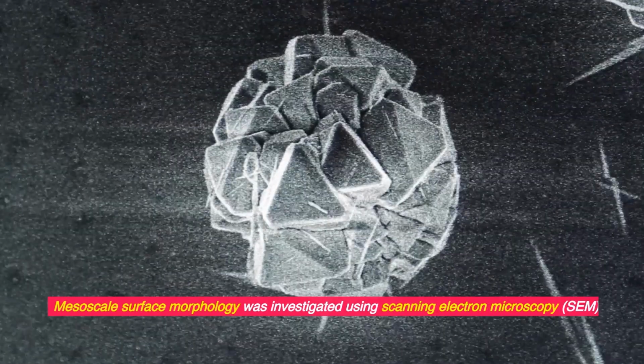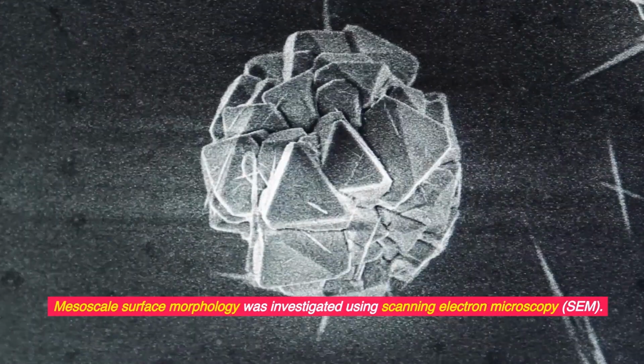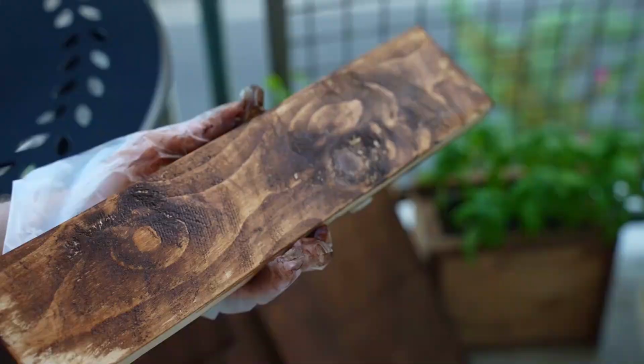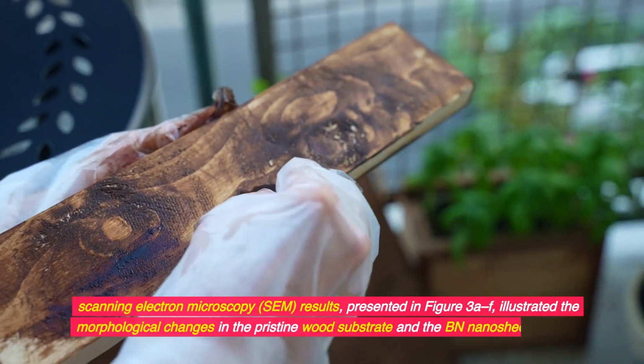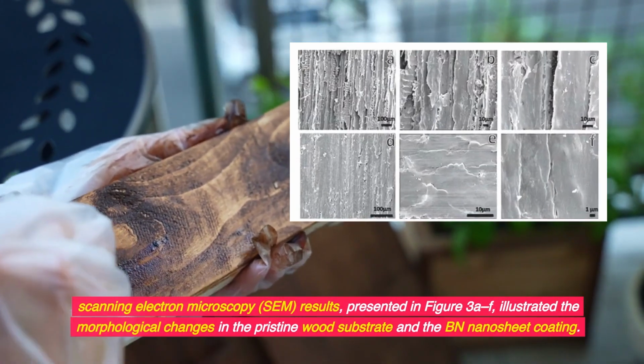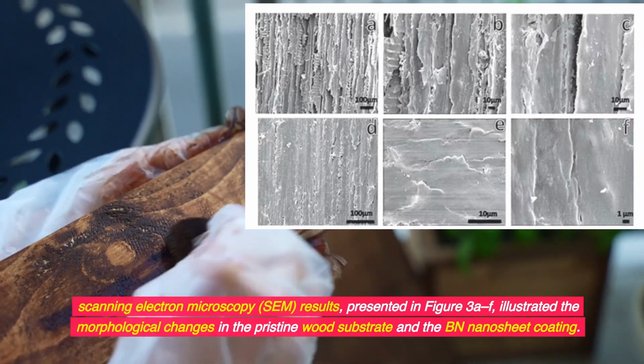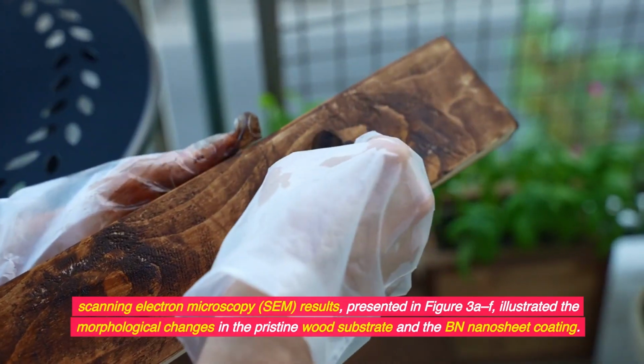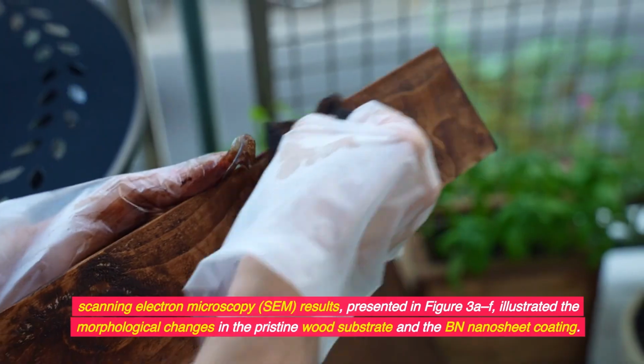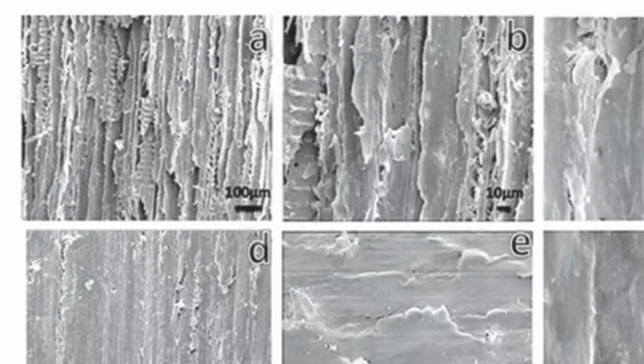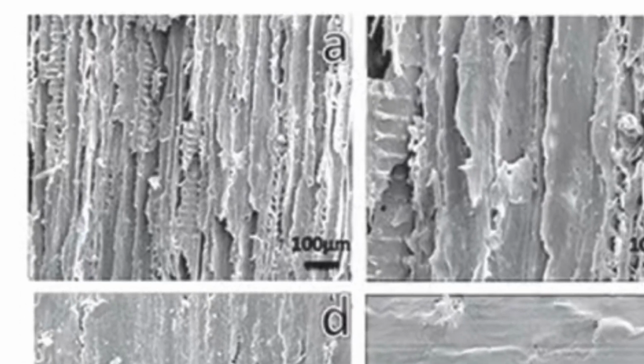Mesoscale surface morphology was investigated using scanning electron microscopy (SEM). SEM results, presented in Figure 3A-F, illustrated the morphological changes in the pristine wood substrate and the BN nanosheet coating. Figure 3A revealed surface grooves in the pristine wood substrate.